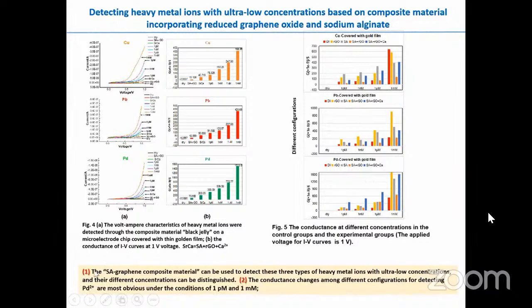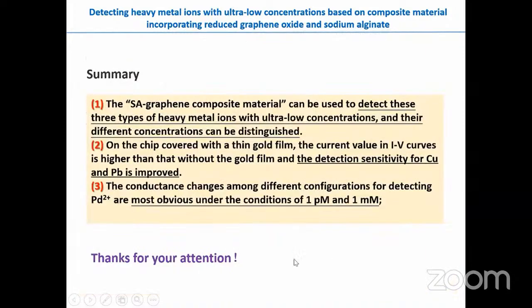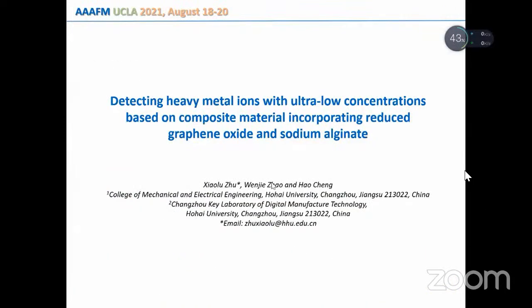From these figures, we can conclude that the SA graphene composite material can be used to detect these 3 types of heavy metal ions with ultra-low concentrations. We can see that the lowest concentration reached is 1 picomole, and different concentrations can be distinguished. The second is that the conductance changes among different configurations for detecting palladium are most obvious under the conditions of 1 picomole and 1 millimole. So here is the summary. Thanks for your attention. Good afternoon.